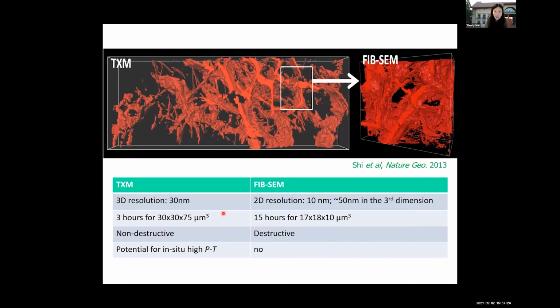And then just a summary, which also shows the smaller portion of the FIB SEM. We can compare our TXMs to the serial sectioning approach, and they are consistent, so that's great. So this is where you use an FIB, SEM image, FIB cut off a layer, SEM image, FIB layer, on to reconstruct a 3D image from many 2D images. Sorry, 3D object from many 2D images.